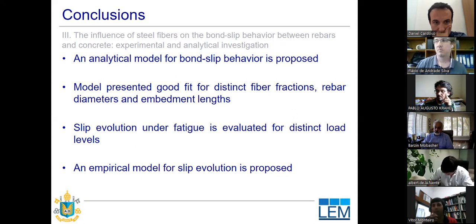And we also could evaluate the slip evolution, which characterizes the degradation of the interface between rebar and concrete under fatigue. So we could evaluate it in terms of empirical analytical equations, the bond slip behavior, and also the pull out under fatigue loading based on those mathematical equations.